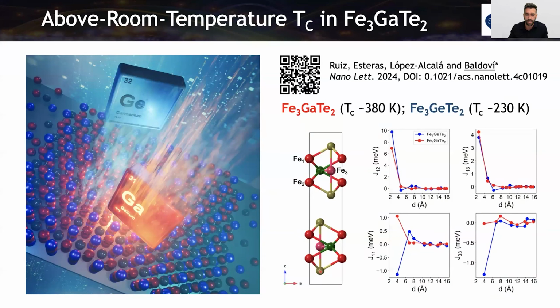So here is the bulk unit cell. In this case, the iron, gallium, tellurium has a Curie temperature of about 380 Kelvin. The case of germanium is 230. And here we have labeled the magnetic atoms, iron 1, iron 2, and iron 3. So we are computing, for example, J12, the interaction between iron 1 and iron 2, the out of plane interaction. This is J13, from this to this. And then we have also this in plane, from iron 1 to iron 1, and from iron 3 to the next neighbor in the next unit cell, iron 3.